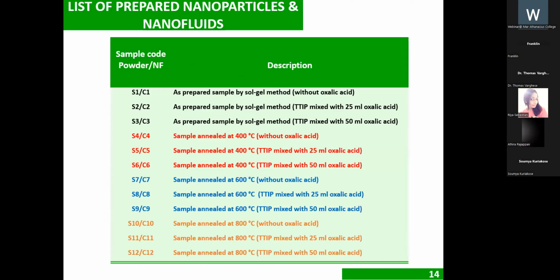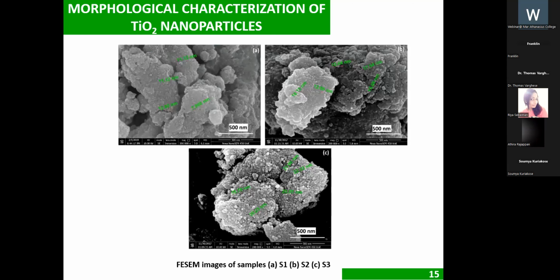So the different samples that I have in this study are 12 different samples in 4 different categories, 4 different temperatures. One is the as-prepared or room temperature, and then the samples with 400, 600 and 800 degree annealing temperatures. And at each annealing temperature, there are 3 different samples: without oxalic acid, with 25 and with 50 ml oxalic acid samples. The morphological characterization is carried out using FESEM analysis, and the morphology is an agglomerated spherical-like morphology